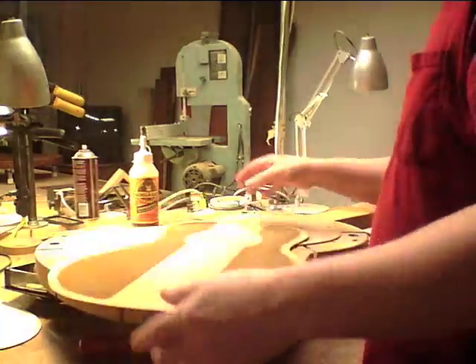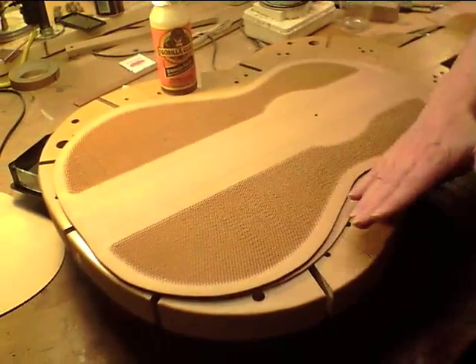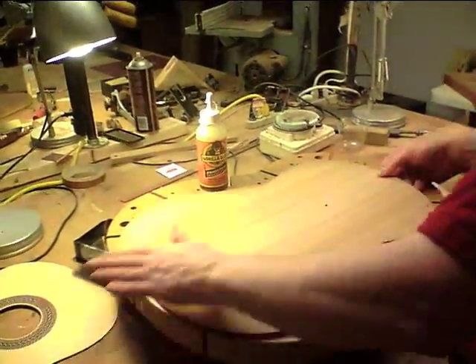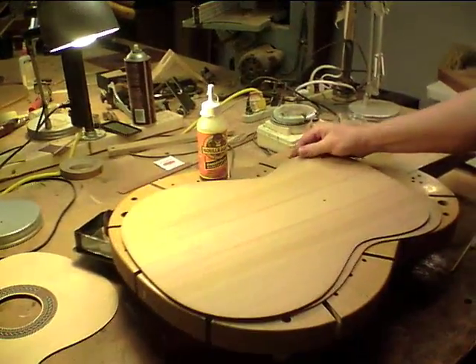You can see there's a little foaming here — this isn't a finished top and I don't have a rosette in there — but this is the outcome of it. The thing about the pockets the way I'm doing it is you get a gradual transition of both the wood and the honeycomb. You can see it feathers here and then feathers in there. I spread the gorilla glue at a specified weight until it just stays a little glossy — as you spread it, it gets dull like it's soaking in, so you go until it stays glossy because you don't need a lot. I've never heard of one delaminating or separating.